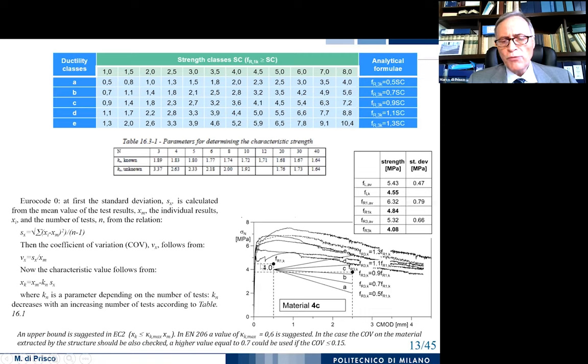So looking, for instance, at this example, we have 6 specimens. We know the nominal strengths computed as a bending moment divided by the elastic bending modulus versus CMOD. We can compute for 0.5 and 2.5 the characteristic value according to the Eurocode 0, so the lognormal approach. And then we compute these 2 points and we can compare with the strength classes.